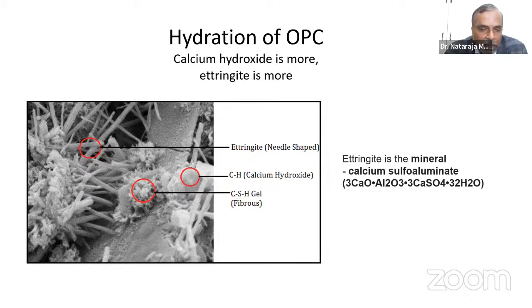So this is a sort of mineral. This is one material responsible for the lack of durability related performance, especially in your concrete. This is what is referred to as calcium sulfoaluminate, which is really a detrimental material as far as ordinary Portland cement is concerned: ettringite. And of course, ettringite can form immediately, or it can even form over time, depending on the situation. My dear faculty, what I would like to tell you is, when you make concrete today, don't use 100% cement. In fact, for 10 to 15 years people have not been using 100% OPC, but I am still seeing many applications where 100% cement is being used. We need to replace a certain percentage of OPC, say 25%, going up to 50%, with some of the supplementary cementing materials.